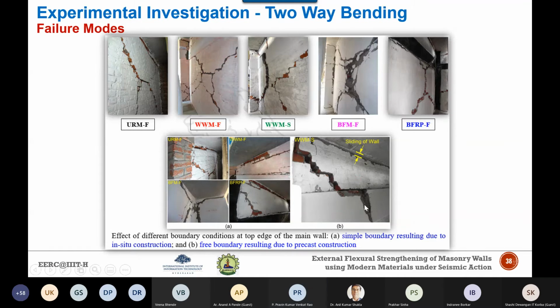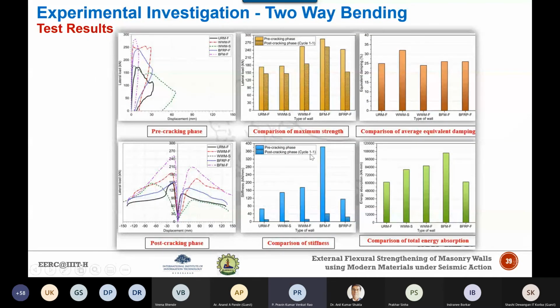Now, here you can see that in all the retrofitted walls, this black line represents the envelope for the pre-cracking phase for the unreinforced masonry, and the other different colors represent the strengthened walls. This green dotted line is for welded wire mesh. However, this is strengthened, but this is with the flexible diaphragm condition, and because of that there is hardly any strength increment. However, you can see that the stiffness is increased significantly, and this is for the post cracking phase.